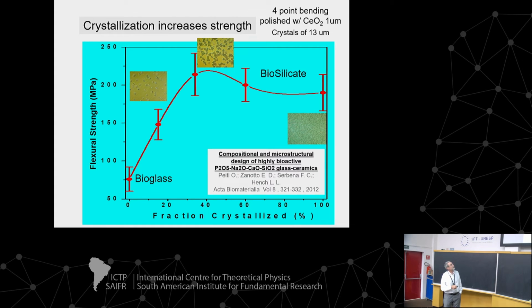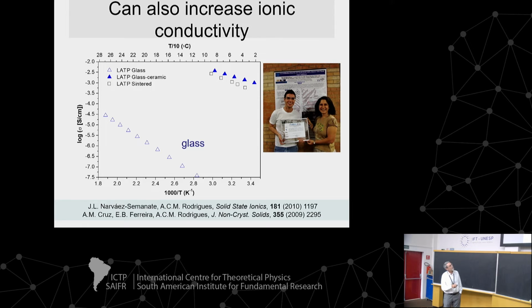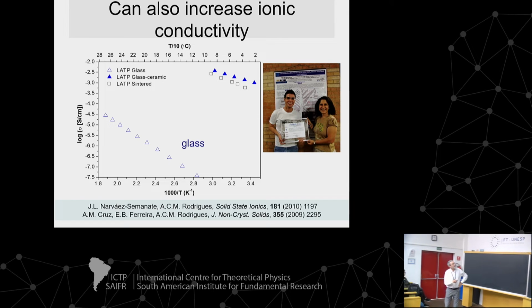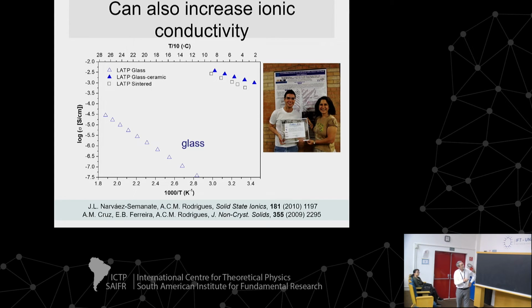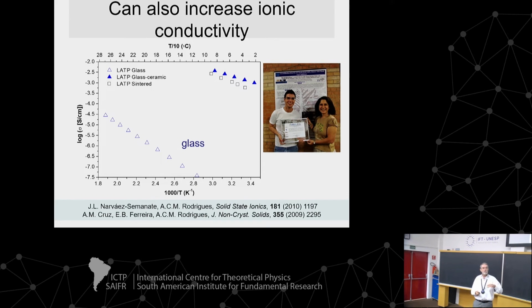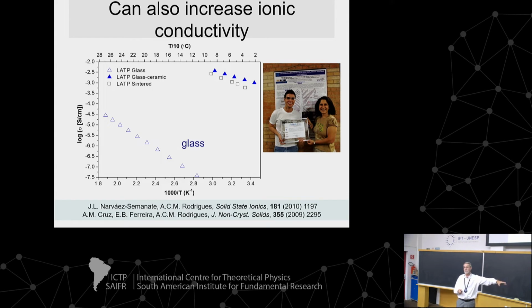Another interesting example is from a colleague of mine, Anna, who works on ionic conducting materials. This is the conductivity on a log scale versus inverse temperature. This is a particular glass. And this is the material after crystallization, a glass ceramic. You see 4 or 5 orders of magnitude increase in the conductivity if you are able to crystallize a properly organized crystal phase. These are materials used for lithium and sodium solid-state batteries.